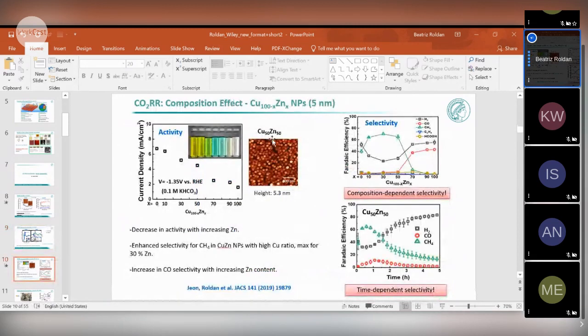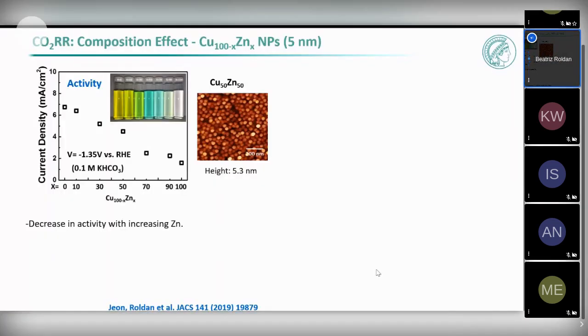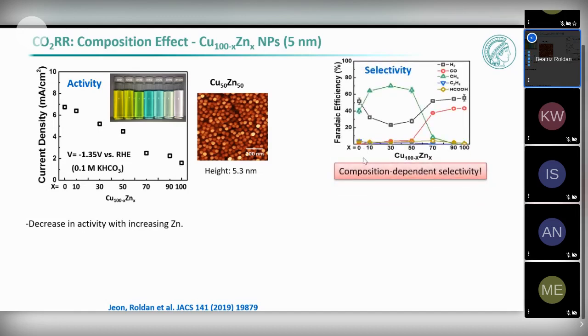So if we now try to combine copper with zinc, we stay with large nanoparticles, in this case 5 nanometers. Here we know that we are not only going to be producing hydrogen, and we wanted to try to see if we can tune the selectivity by changing the... sorry, I think I was not sharing the entire screen, sorry. So we can change the selectivity by increasing the content of zinc. So here you see that with increasing zinc content, we can see a decrease in the current density, so a decrease in the activity.